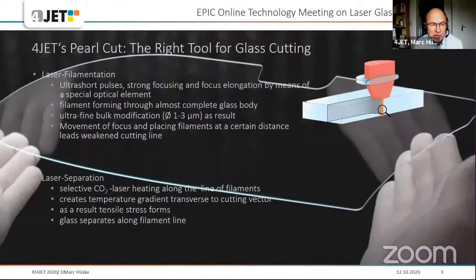Now, we call it pearl cut technology, which is actually based on the filament cutting to cut glass and achieve the perfect edge, which is a perpendicular edge at the glass edge where the filaments have been formed. And this edge is too perfect in some cases because it doesn't have a bevel at the edges. Anyhow, what we use is an ultra-short laser pulse. It's strongly focused, and the focus is elongated by means of special optical elements. A filament is forming in the glass, so we have a chain of little microfractures in the glass along the propagation of the laser beam, resulting in ultrafine bulk modifications of 1 to 3 micrometers in the glass. And this is a weakening, basically, of the glass.